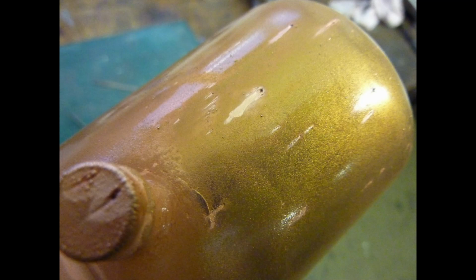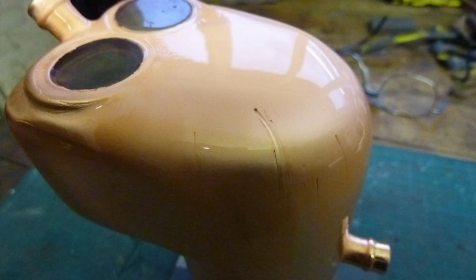Of course, it becomes very tempting to take the thing out after a few hours plating and have a close look at it. With hindsight, I'm not sure this is a good idea because while out of the bath, the copper will immediately start to oxidize, and that may well inhibit the adhesion of a subsequent layer. I got the idea that the process is rather like painting. For the best finish, you rub down between coats, getting rid of all the imperfections. Then with luck, the final coat will be free of blemishes. But this technique may well be wrong.